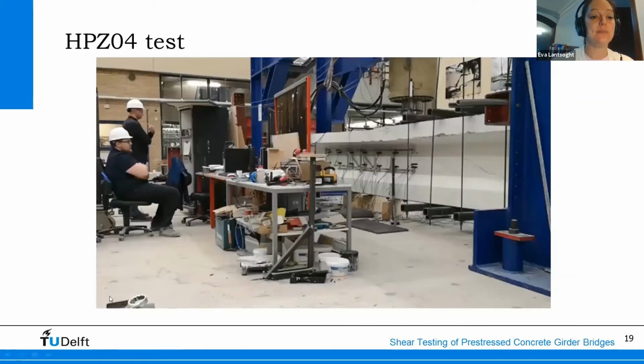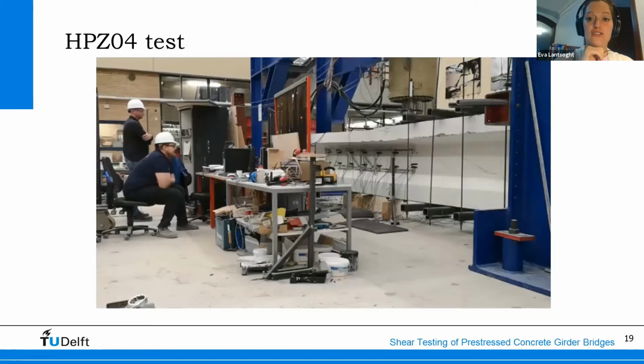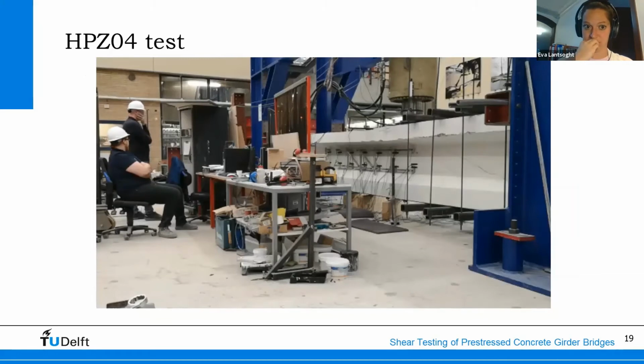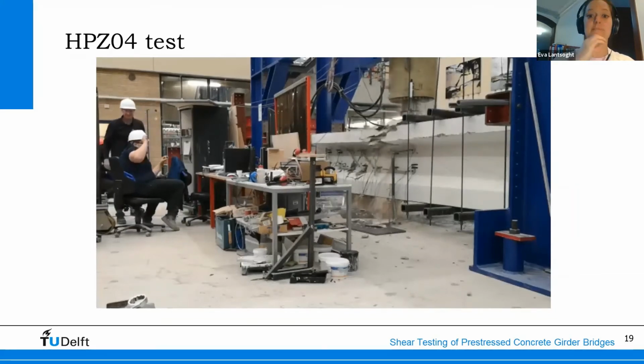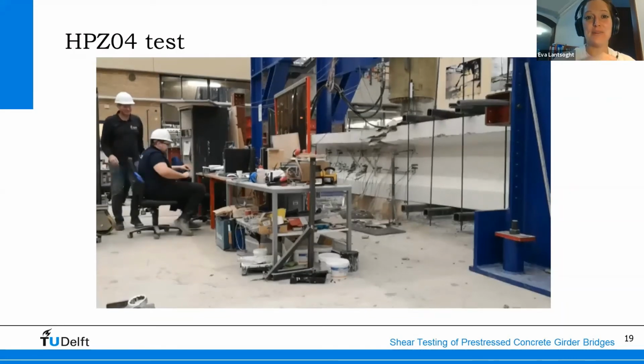Here's the last experiment, or the recording of the last experiment. You can see that here we are using a larger jack, since in HPZ03 we had a maximum load that was very close to the 2000 kilonewton capacity. In this case, we used the 5000 kilonewton jack. So as you can see, a brittle shear failure.